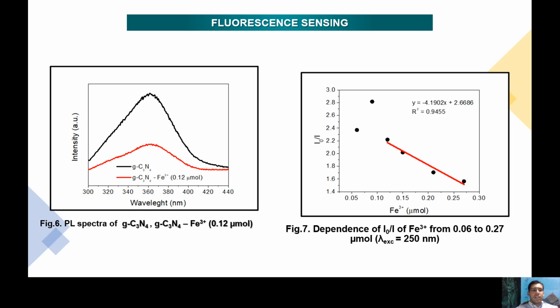For fluorescent sensing, in figure 6, we can find the photoluminescence spectra of the C3N4, and we compare this spectrum with the photoluminescence spectrum of the C3N4 with the iron metal ion, and we can find the quenching effect for the emission band around 370 nanometers. And also with this value, we made a calibration curve, and we can find it in figure 7.